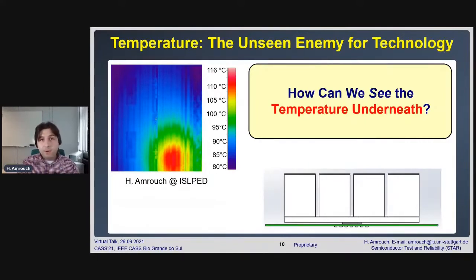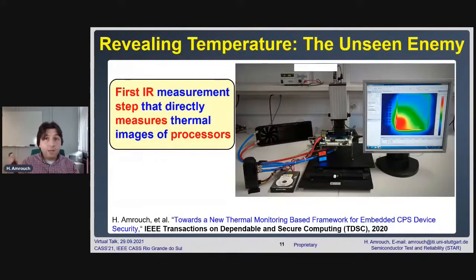In order to solve this problem, we have built the first infrared camera, the first thermal setup that can measure precisely the thermal map, the entire thermal image, for modern processors without any layer in between. That means you have your infrared camera measuring directly the infrared emissions of your silicon die, which allows you for the first time to see how the temperature evolves in those complex modern chips, in order to analyze it at the design time and understand how the temperature can really evolve at the runtime.